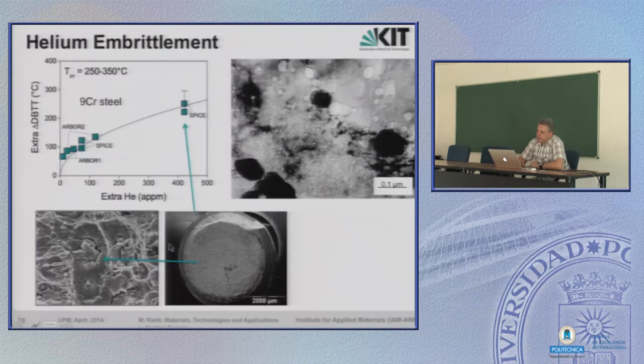And if the helium bubbles arrange themselves at the grain boundaries, you see here easy crack formation around these grain boundaries, and this causes in the end brittle fracture which is only due to helium formation.